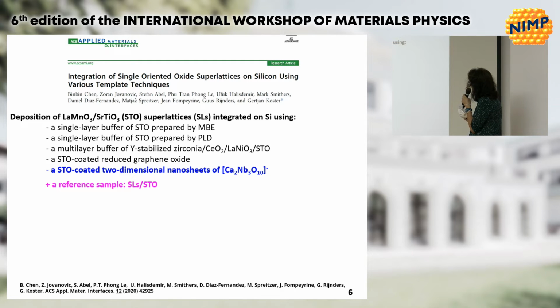Here I present the result of a publication from last year, actually. In this article, different groups have worked together to compare all these methods I have shown to you. They have deposited a superlattice of manganite plus strontium titanate on silicon using a single-layer buffer of strontium titanate by molecular beam epitaxy, also by pulsed laser deposition, other template layers, and so on. And they have compared also with a strontium titanate thin seed layer on two-dimensional nanosheets, plus a reference sample.